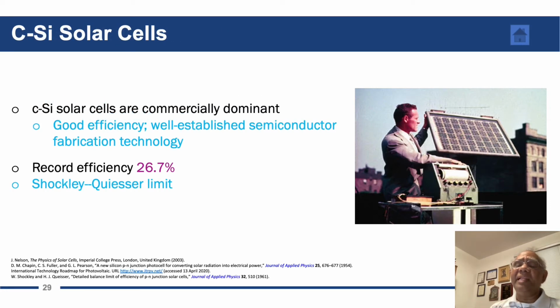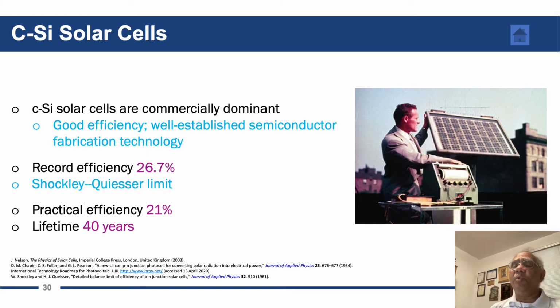Today, solar cells made of crystalline silicon are well established commercially. The record efficiency is 26.7%, quite close to the theoretical maximum called the Shockley-Queisser limit. Practical efficiency is about 21%, and the lifetime of solar cells is estimated at 40 years.